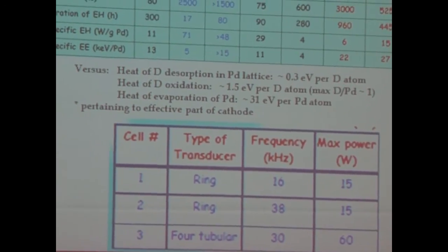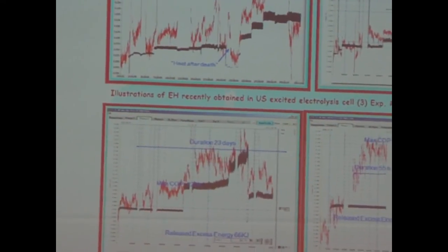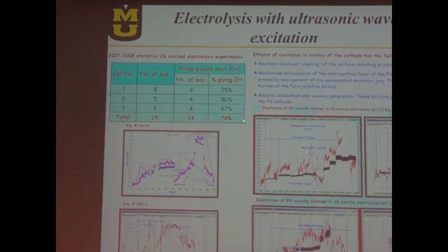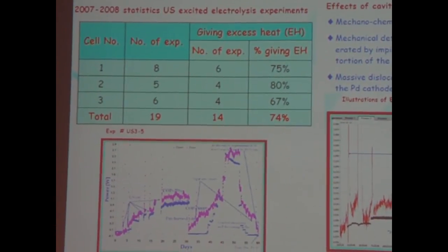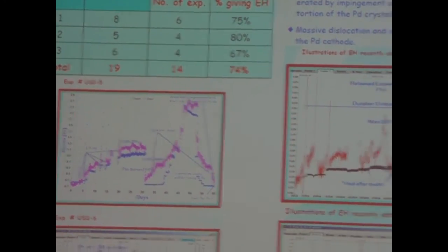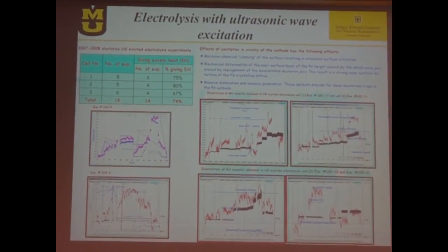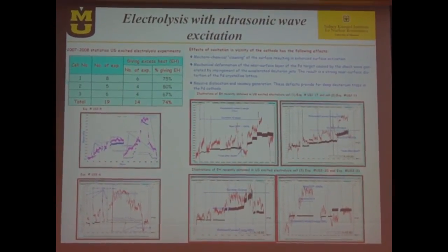And that in some lots we got up to 70% reproducibility, and this is some of the results. You can see here 75%, 80%, and in average 74%, but there were a lot of failures from other lots, which reduced these nice numbers of reproducibility.